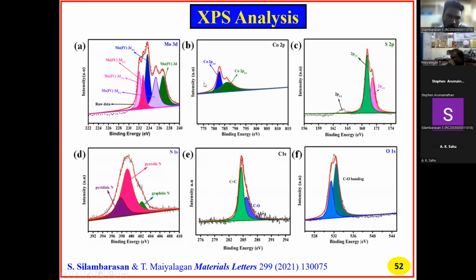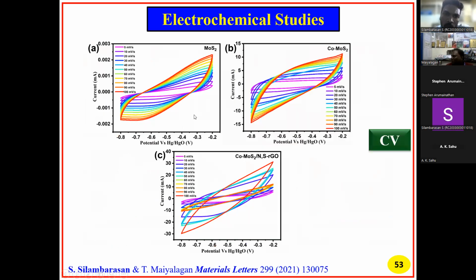Next, XPS analysis. Here we confirm molybdenum, cobalt, sulfur, nitrogen, carbon and oxygen; all these elements are confirmed from the XPS. Then there is cyclic voltammetry. Figure A is for MoS2, where the applied scan rate is from 5 to 100 millivolt per second, and figure B is the cobalt-doped MoS2, and figure C is the cobalt-doped MoS2 with NSRGO composite. Compared to the others, figure C gives a measured current of around 33.